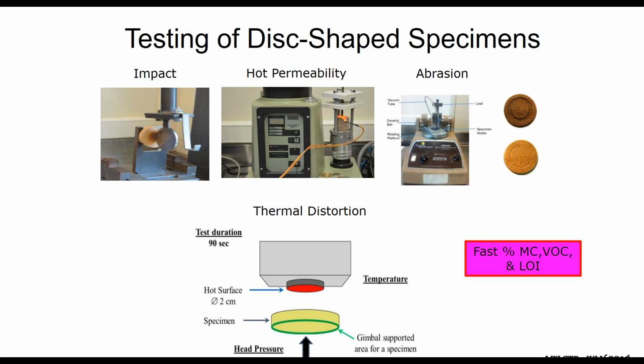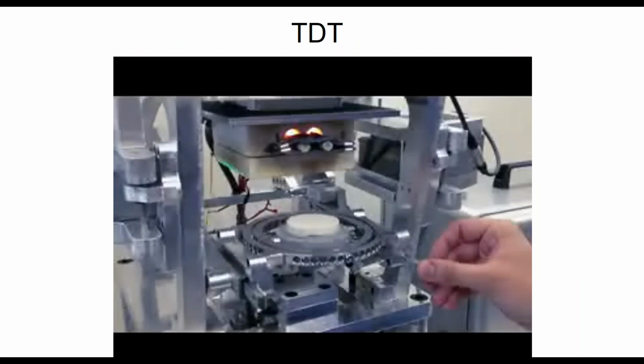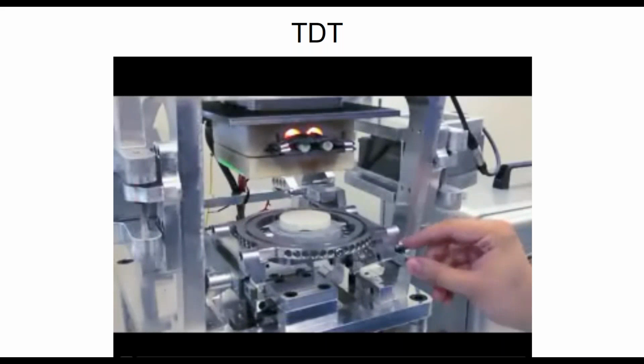So the hot permeability test is telling us, can we really vent when the action is really happening, when we put heat onto that sand system? And then the abrasion test will tell us about cure characteristics, hot to cold. But the preeminent tests around these are two. We can do a fast LOI, a VOC, and moisture in less than 5 minutes. But the preeminent test that gives us time series data, which is also part of smart data for process control, is the thermal distortion test, also known as TDT.